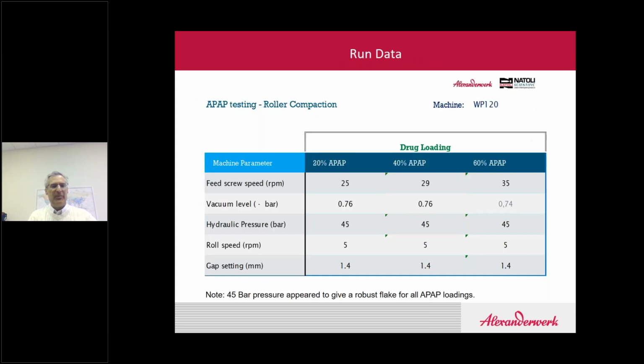Our parameters that we ran the system at, in order to be consistent across all 3 tests, were a hydraulic pressure of about 45 bar, roll speed of 5 RPM, and a gap setting of 1.4 millimeters. As you can see, the feed screw speed had to increase accordingly from the lower drug loading to the higher drug loading. Feed screw speed at the 20% APAP loading was around 25 RPM. At the 40% APAP loading, we were at 29 RPM, and the 60% APAP loading was around 35 RPM. These are the average speeds that the machine ran at.